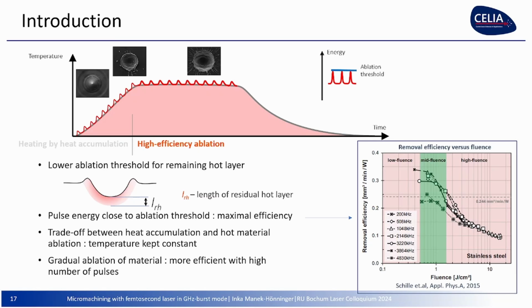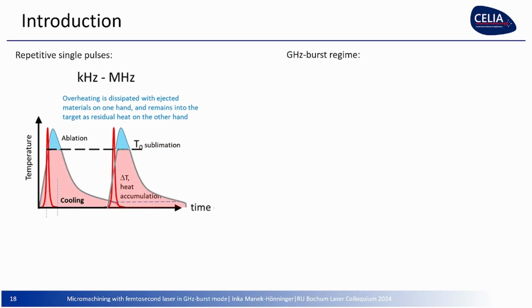So of course you have to find a trade-off: a good way of heat accumulation, not too much, to avoid unwanted detrimental effects of heat, and on the other hand the most efficient way to ablate. In summary, with repetitive single pulses in the kilohertz or megahertz regime, the pulse comes and heats up the material, and the part of the energy exceeding the ablation threshold contributes to ablation and takes heat away. Then the material cools down, but not completely. There's some residual heat left.